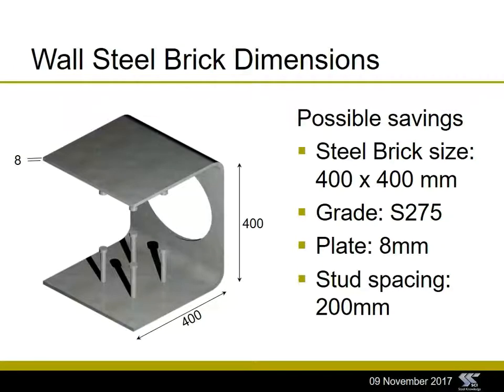Yeah, the American specification specifies a minimum grade of 350, S355. In the European, and the reason for that, if you look at the background to it, is to prevent yielding of the plate during concreting. We've actually opted to say you need to check that in the calculation, depending on whatever grade you're using, to ensure you don't get yielding. But we don't automatically limit you to an S355. Okay.